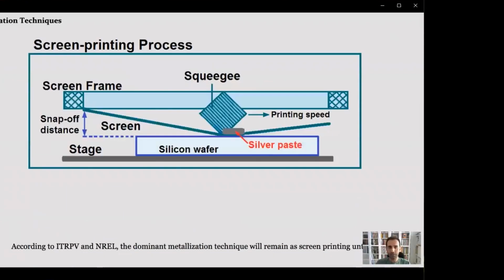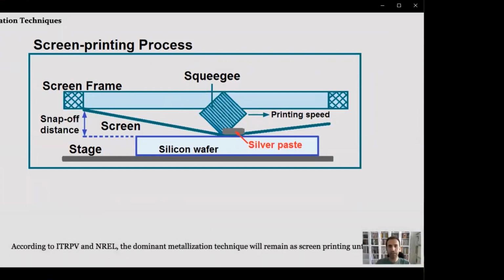The basic principle of the screen printing process is simply to use a mesh screen to produce the same pattern over and over again on silicon wafers with a metal paste. During the printing, paste is first applied to the screen before the movement of the squeegee. As the squeegee moves the paste across the screen, a shearing action causes a decrease in viscosity, allowing the paste to pass through the mesh openings to the desired silicon substrate. The main factors that influence the printing quality are related to the screen, squeegee, and the metal paste.